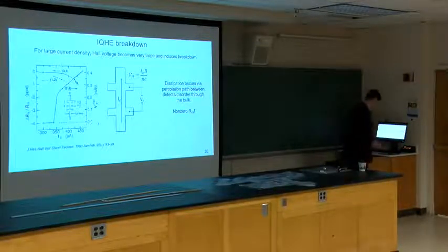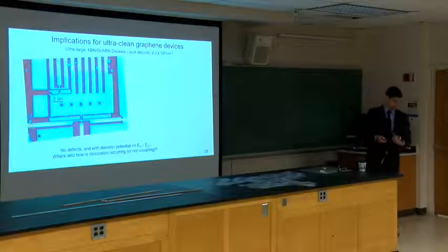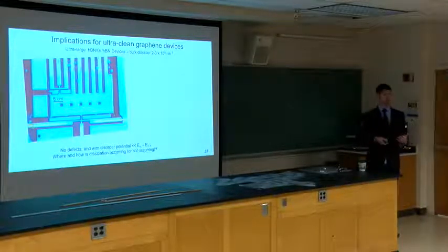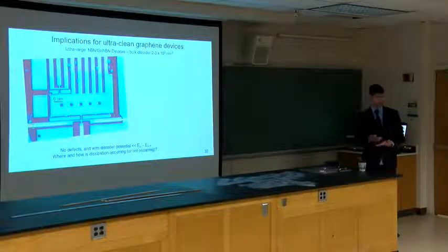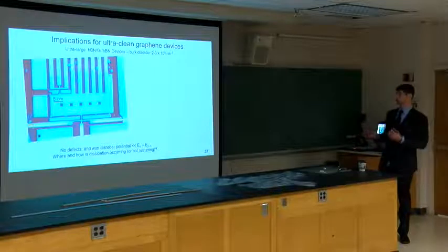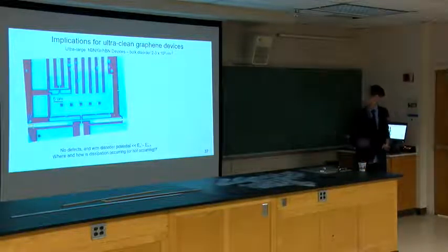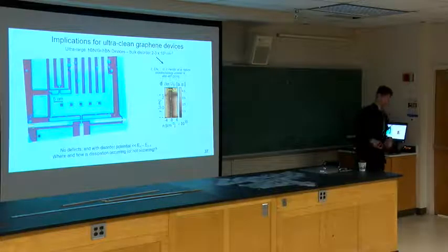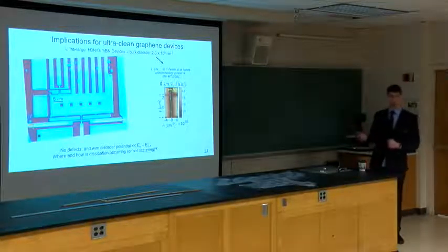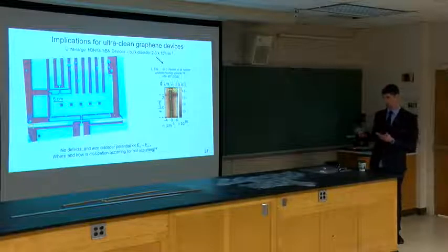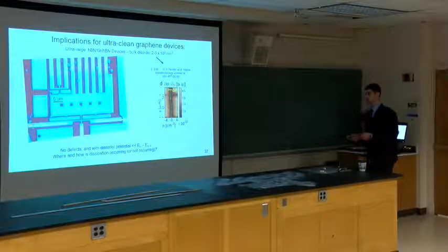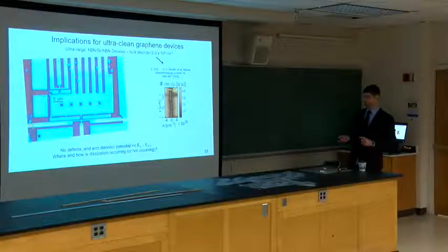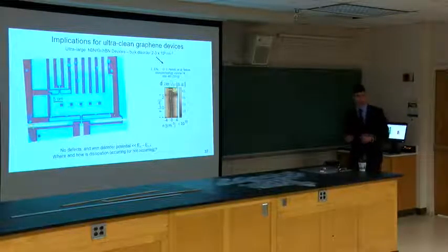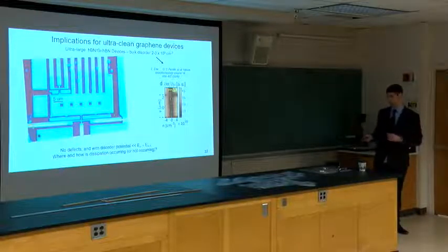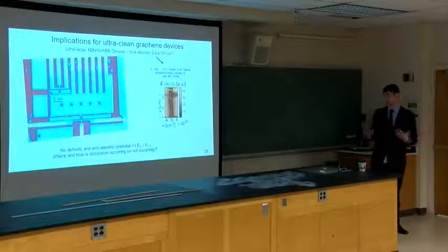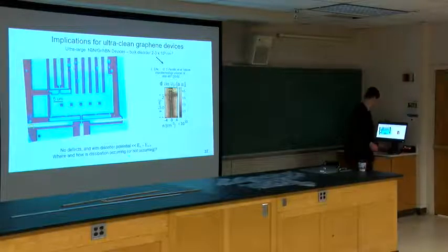So what we want to look at, though, is what if we're looking at a system that has essentially no defects, where the charge disorder in the bulk is so low that there really shouldn't be a percolation path. So the bulk disorder in devices like this is somewhere between 2 and 3 times 10 to the 9. So it's a little bit higher than in the previous device that I showed, but that one was actually graphite gated, and this one is not. And the disorder potential is significantly less than the Landau level spacing at any point in the sample. So can we still have this percolation path, or does dissipation actually occur?